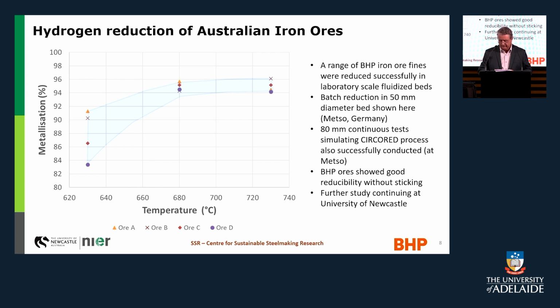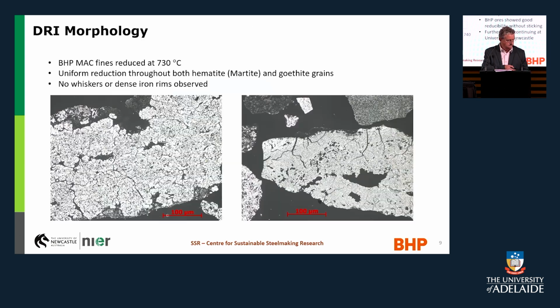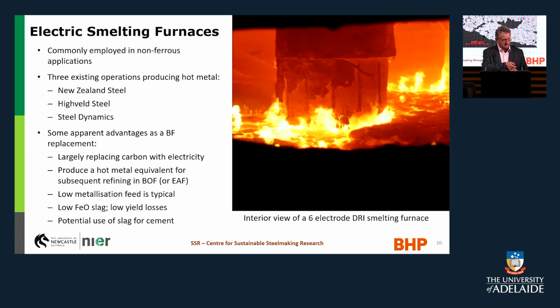And in some ways that spurred us on to try and do some of that hydrogen reduction of iron ore fines directly at University of Newcastle. So we've taken some lessons from Metso and we're doing some of that ourselves now. This is an example of some of that hydrogen reduction work. And Tom was simply wanting to show here that we've taken some BHP MAC fines, reduced at 730 degrees C, and he's wanting to say that we've got a uniform reduction through both hematite and goethite grains, and most importantly, no whiskers or dense iron rims were observed, which were known to be a problem for the sticking issues in Finmet.